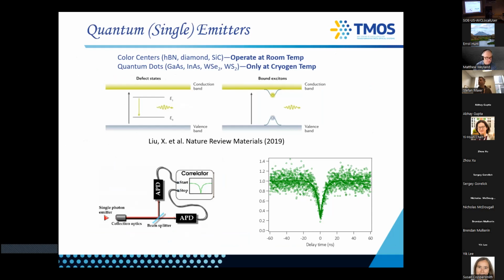So what is a single photon source? Just to get us on the same page. It's an isolated quantum system, basically an artificial atom in a solid. And there are two types of solid state sources you can imagine. Most of you are probably familiar with both of them, but you can think about your levels detuned from the valence and the conduction band. These are your typical quantum dots that have been around for many years. So you just introduce a slight energy detuning, and then you have a trapped quantum dot, and it will emit single photons, typically limited to cryogenic temperatures.